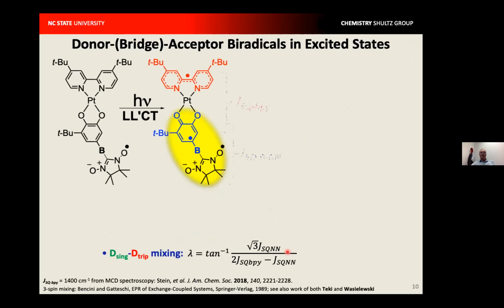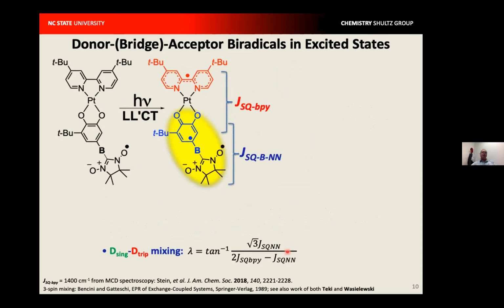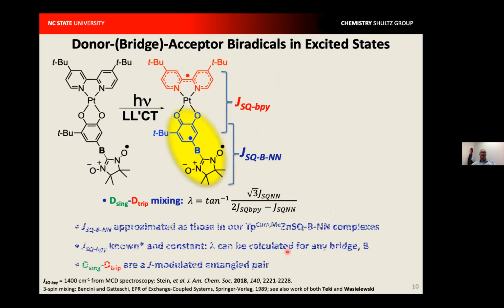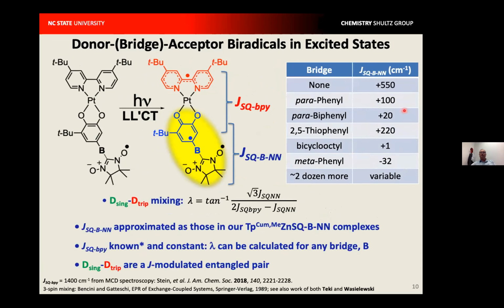So here are some examples of what the exchange parameters are for these excited states. These exchange parameters come from the zinc complexes that are not shown on this slide, but if there's no bridge and you directly attach the semiquinone and the nitronyl nitroxide, you get strong ferromagnetic exchange of the semiquinone and the NN. A para-phenylene bridge reduces that exchange coupling to about 100 reciprocal centimeters, giving a singlet-triplet gap of 200 reciprocal centimeters.